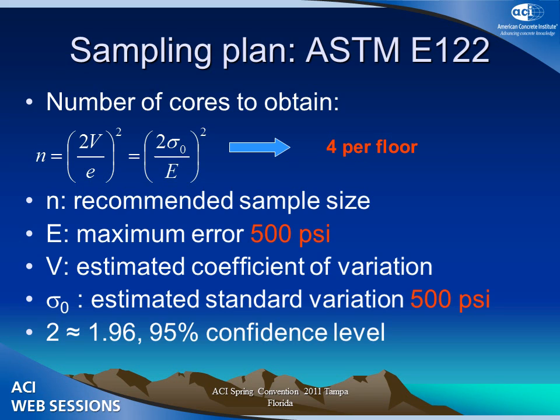We were also fairly confident that since this structure was built at about the same time, there wouldn't have been a lot of variability, and actually all of that concrete is the same concrete. We ended up with a population of 51 cores, which would far exceed any number you get by plugging in other numbers. We wanted at least 4 cores from each of the floors so that we could do a little comparison to validate whether there was a difference among the floors in the structure.